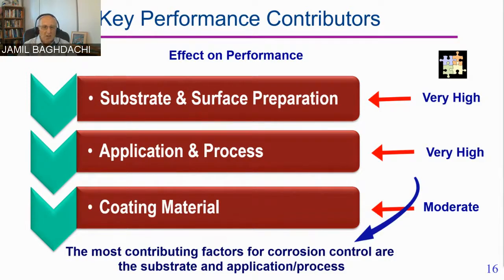Material, of course. Typically, the coating materials play a major role, but you may have the best coating in the world, and if the substrate is not right, it's not going to do a good job. Or if the application was wrong, it's not going to do a good job either. Most of the time, the users go after someone who made the paint. I am not the one to make paint. I'm not taking any sides, of course. But we figure out that the paint was good, but one part of a wing is good, better than the other one. So that means the paint was really good, versus the thickness or thinness of the coating. Next, please.